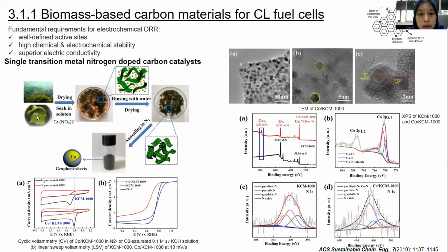Okay, this is a paper about the utilization of biomass waste as ORR catalyst. The biomass material usually needs to be pre-treated and converted to a catalytic composite to fulfill the fundamental requirements for electrochemical ORR. The material for electrochemical ORR should have well-defined active sites, high chemical and electrochemical stability, and also superior electric conductivity. One well-known method to synthesize catalyst material for ORR is the single transition metal nitrogen-doped carbon catalyst, or we call it MNC catalyst.